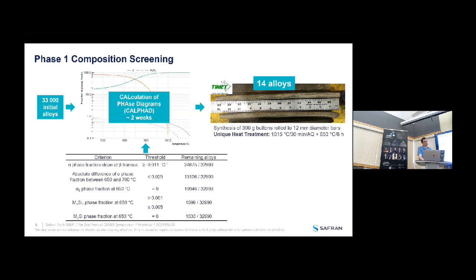So we do a lot of calculation of phase diagrams in this kind of materials because the databases are commercially available, and it makes sense to consider equilibrium calculation for high temperature material, because during their service, they tend to adopt the predicted microstructure. So I'm not going to go into too much detail. The idea is that we don't consider these calculated results as absolute results. We use commercial alloys as reference, and we try to compare the calculated results with that of the commercial alloys to identify alloys that are less sensitive to fatigue, for example, as expressed by a number of criteria that we relate to phase diagram.